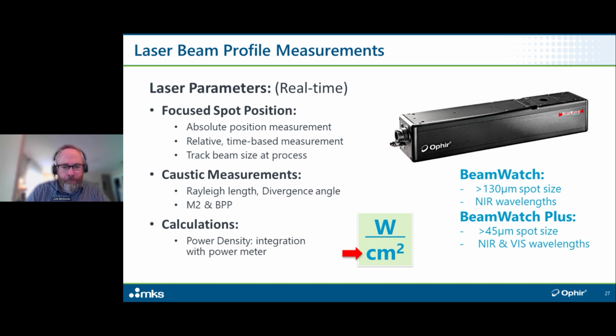As far as the measurements that we get from the Beam Watch, absolute position measurement. So if you need to verify the absolute position of your focus spot periodically, this is the device to do that. And then it also gives you relative time-based measurements of your focus spot size, so you can track the beam size and the spot location in real time. It will also give you real-time caustic measurements, so your Rayleigh length, your divergence angle, your M squared and beam parameter products. As soon as you turn the laser on, you are getting measurements of all those very important laser characteristics.